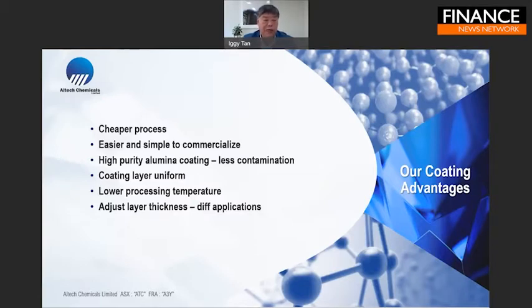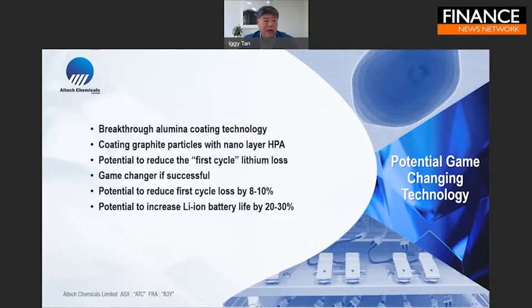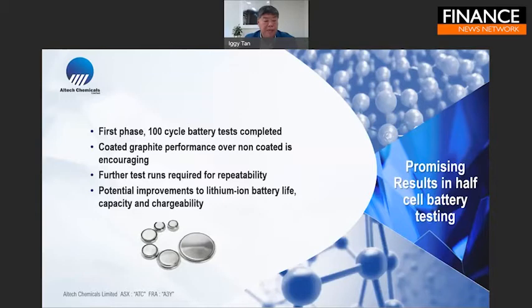Because we're using high purity alumina, there will be less contamination to the battery. And you can see how the coating is very uniform. And because we use very low processing temperatures, our cost difference is significant. So we think this is breakthrough technology, and we think this is a game changer for the lithium-ion battery industry. We have now done the test work in batteries with coated graphite, and we see very encouraging results of coated graphite versus non-coated graphite. So it certainly performs better in the battery.